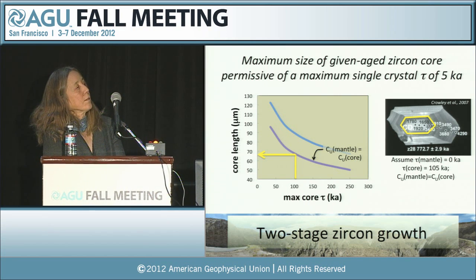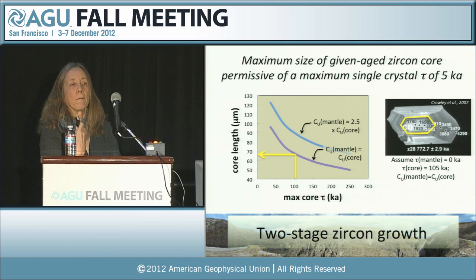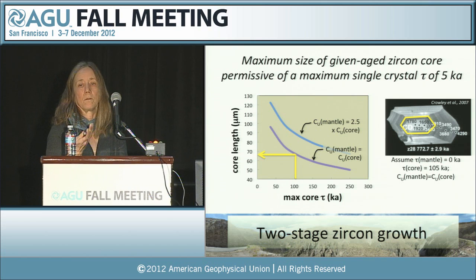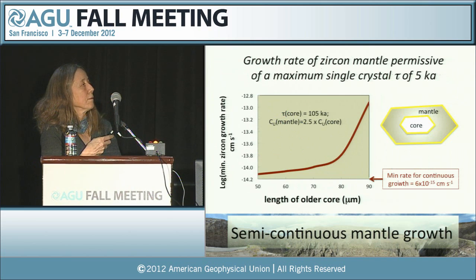I've compared it here to the cathodoluminescence imaging of Crowley et al., and you can see that they identified a core domain within this that's somewhat smaller than the domain that's permissive by this mass balance calculation. In addition, they also found that the concentrations were lower in the cores than in the rims. And so if I allow for those differences in concentrations, I can have an even bigger core at 105,000 years. An even bigger core would be permitted, and still might not be easily detected in these single crystal analyses.